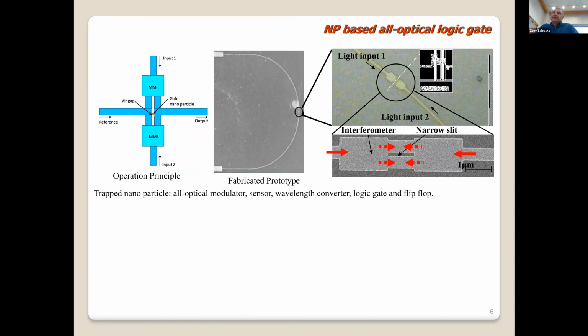But before doing that, I want to say that this technique can be further extended, and not only for an electro-optical modulator, in which the shift of the nanoparticle is done by applying electrical fields. We can also do it in an all-optical modulator in which we have the input. This is the input. This is where the nanoparticle is. And the shift of the nanoparticle is done by an additional second photonic input that generates a photonic interference within this gap or hole that we have fabricated. And by changing the relative phase between those two inputs, the interference fringes move and they shift the nanoparticles with them due to the gradient forces, photonic forces.